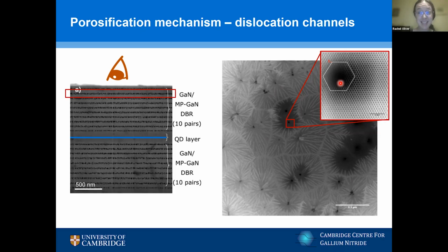The dislocation is basically still there because the displacement still exists. But the distorted region of bonding at the very, very heart of the dislocation has been etched away, leaving behind a pipe down which our etchant flows. And that's how we can etch through these undoped layers to access the doped layers below and create these multi-layer distributed Bragg reflector structures.